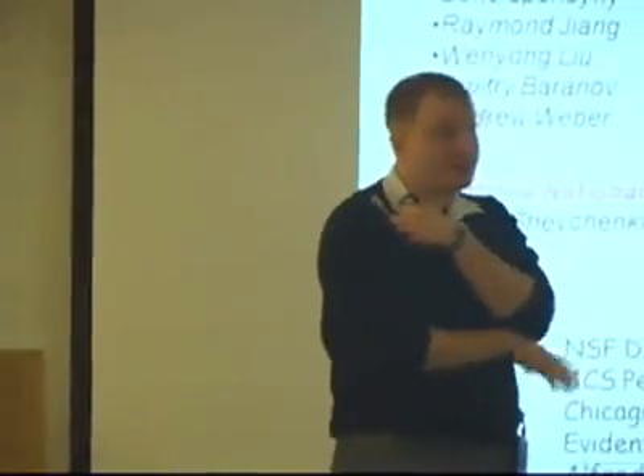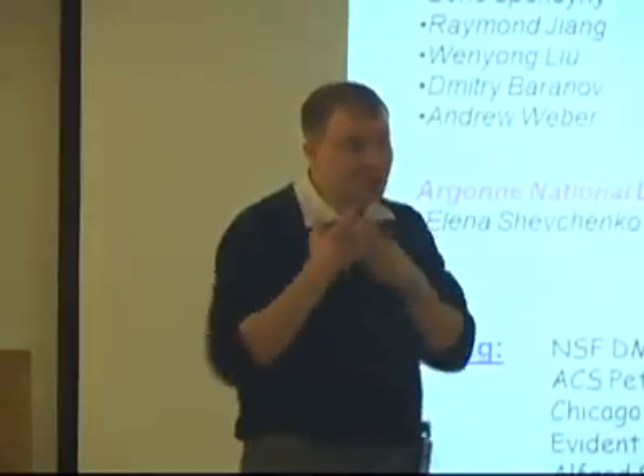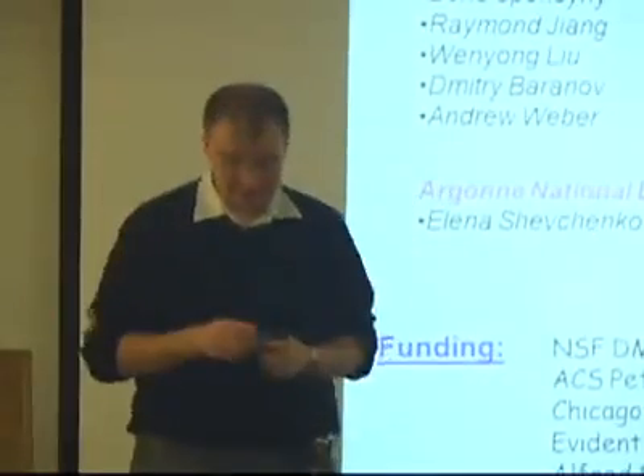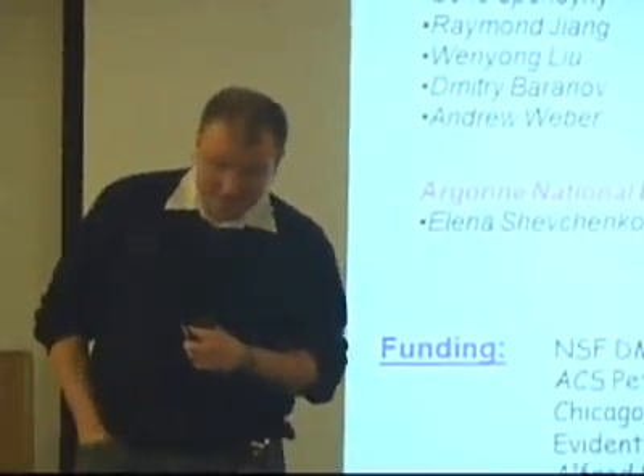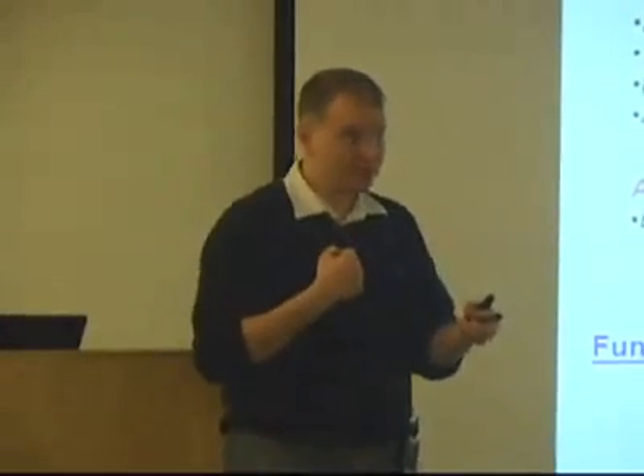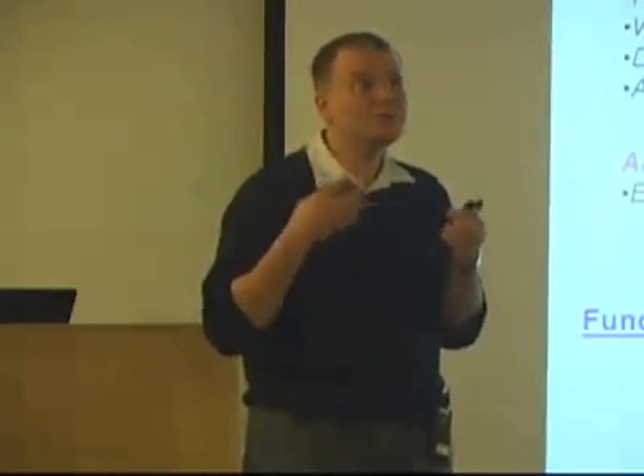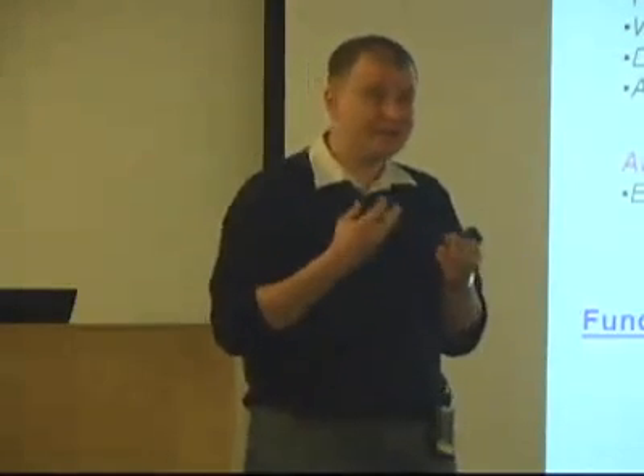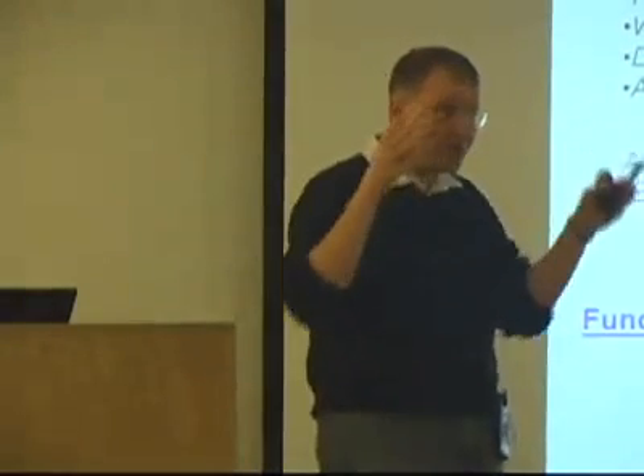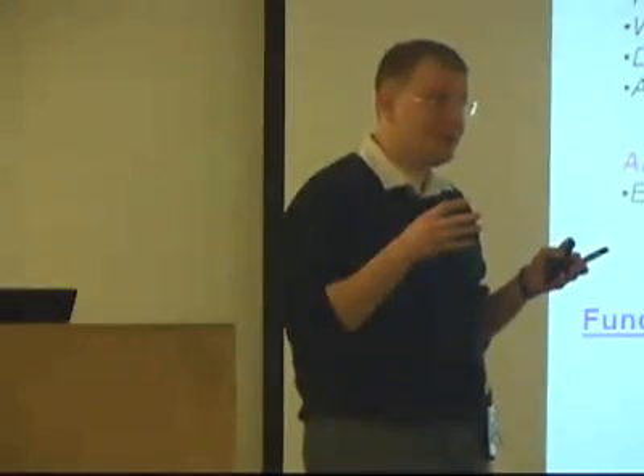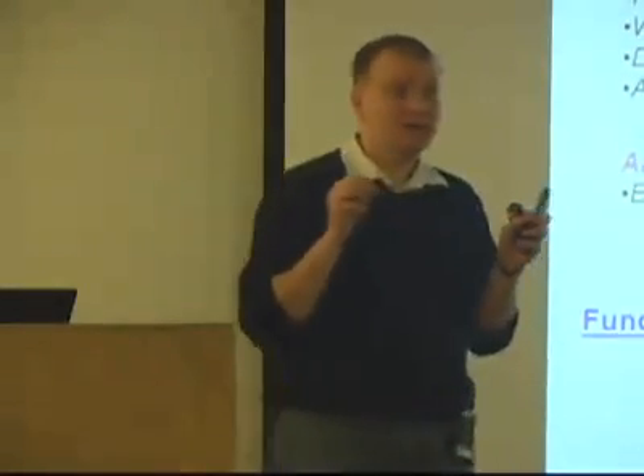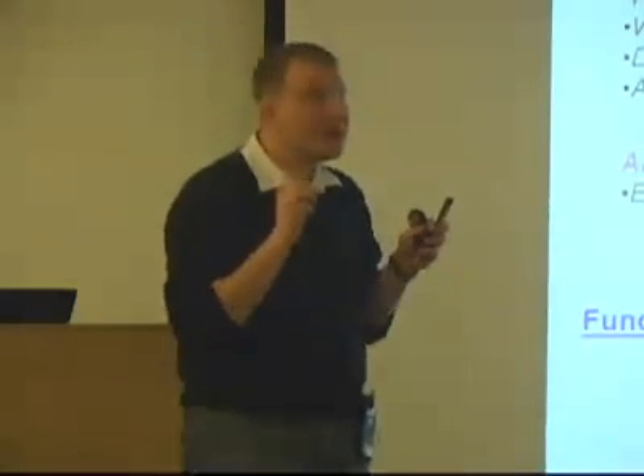That's possible, but we did not have much luck with similar approaches. What we found is that you can use brute force to strip off ligands. But the problem is that you have to do something with the dangling bonds, with the under-coordinated surface sites that are always present at the nanoparticle surface. If you have nothing there, then you will generate a high concentration of surface traps.